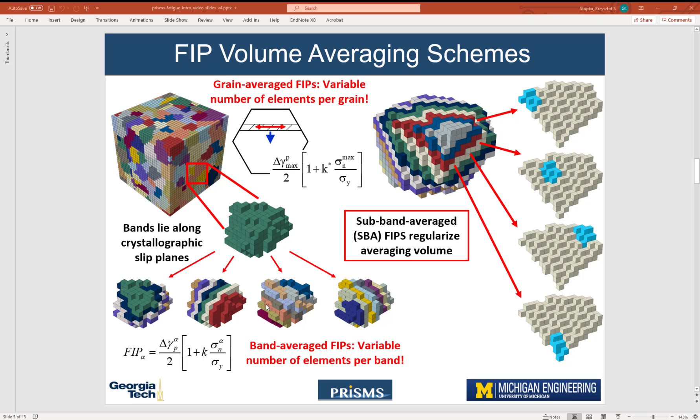So this means that every element then is part of one layer, one for each of the four slip planes. So this is to replicate in the real material the atomic slip planes.